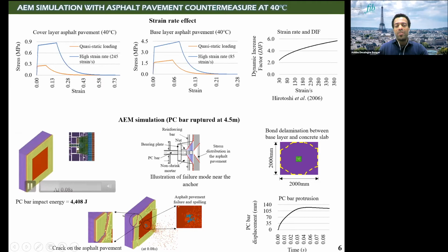And as you can see, the asphalt pavement is severely damaged near the anchor. And we also observed that there is a big crack around the corner like this. And we also observed that there was severe bond delamination between the concrete slab and the base layer. So when the bar is impacting the asphalt pavement, since the position is vertical, the entire pavement system will fall down. This is the PC bar displacement versus time. In fact, the bar is impacting the asphalt pavement, and finally, when displacement reaches 130 millimeters, it stops moving.